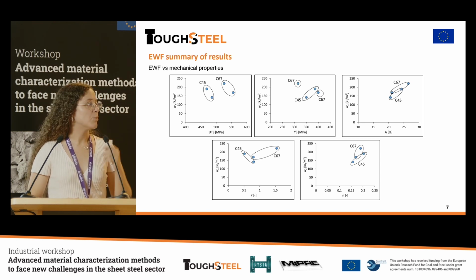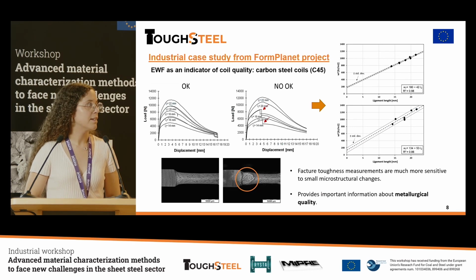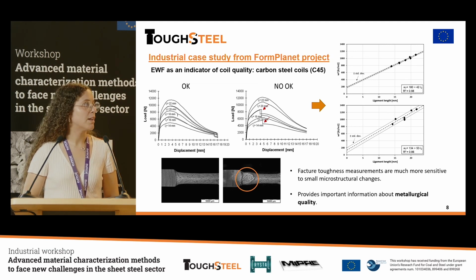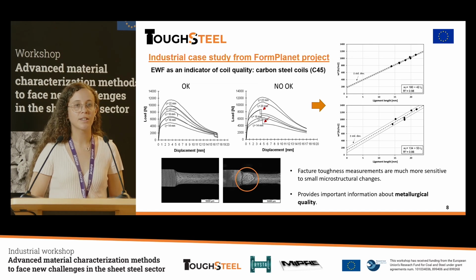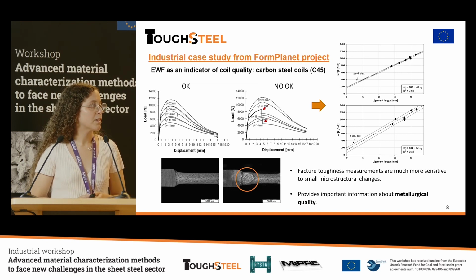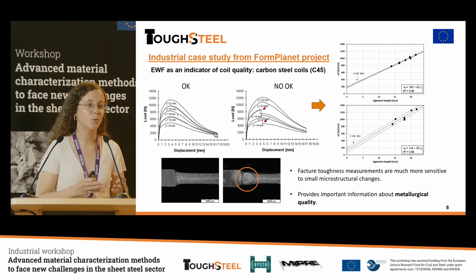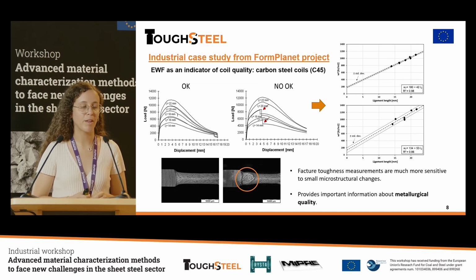Next on, we can see another industrial case study that we performed in the frame of the FormPlanet project. In this case, we studied also two carbon steels, C45, and in this case, we had 2 different coils from the same steel grade. We had these 2 coils, one presenting some cracks in the forming process, and the other not presenting them. However, the mechanical properties were similar for all of them.